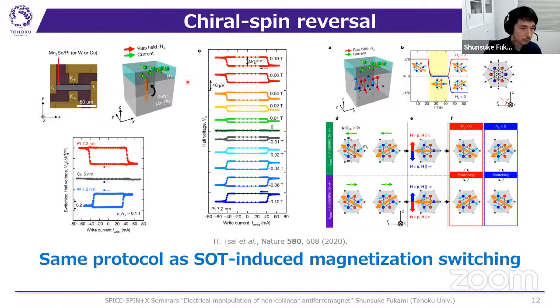So they prepared bilayer structures consisting of polycrystalline manganese-3 tin and platinum, and they apply a current in these directions. And when they apply the magnetic field along the X direction, the switching of the Hall voltage is observed. And when they replace the platinum by copper, nothing is observed. But when they replace platinum by tungsten, the opposite behavior was observed.